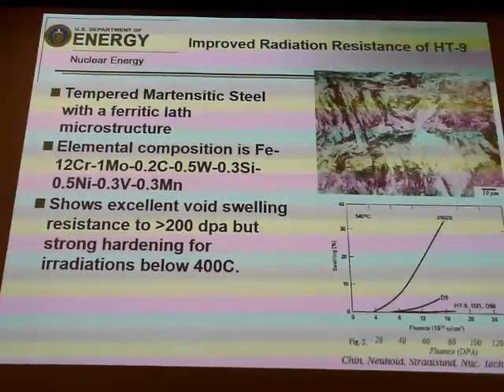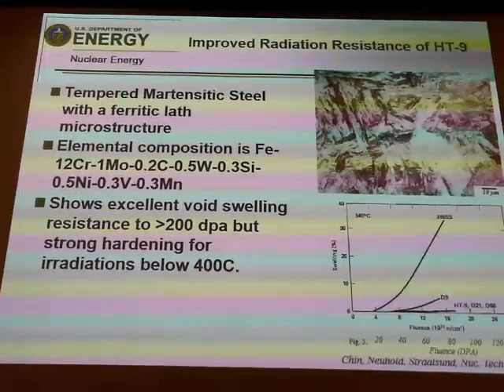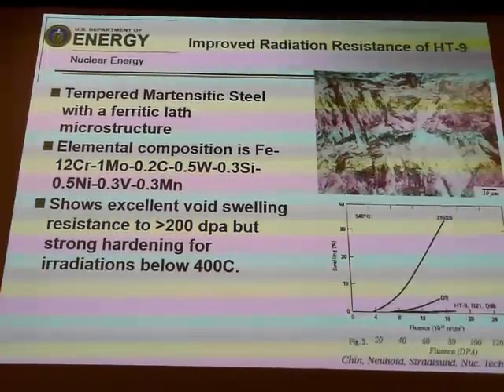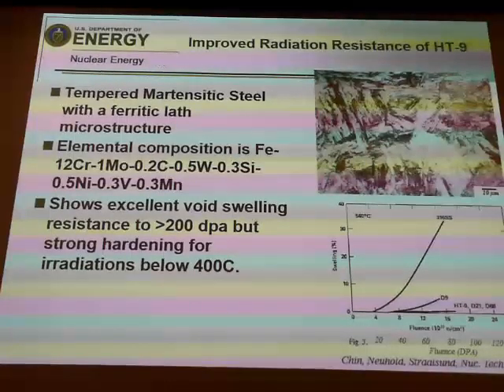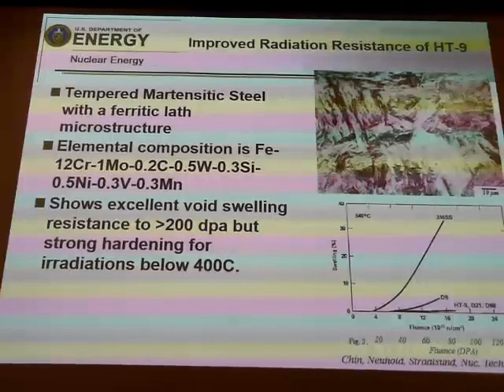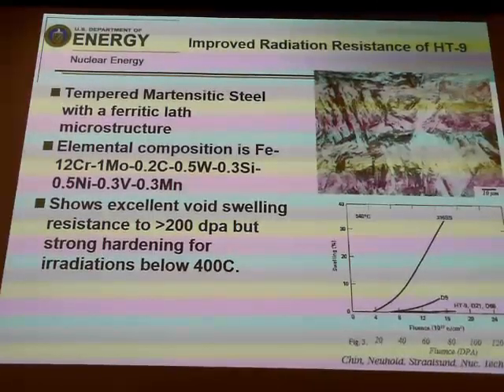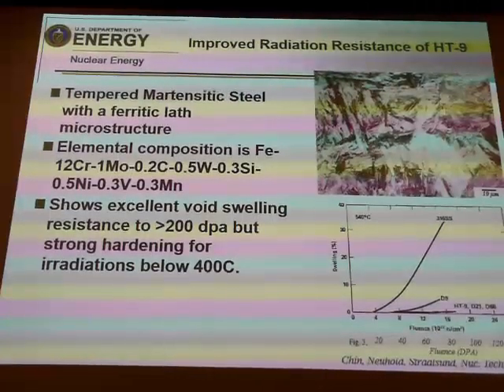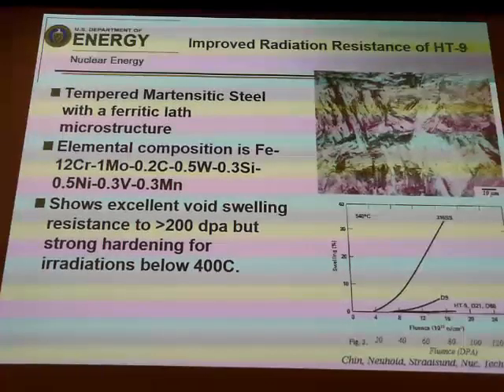And what is HT9? It's a tempered martensitic steel that has a ferritic lath microstructure. This is an optical micrograph of a typical tempered HT9 microstructure, and it's got a fine distribution of laths that are tempered to ferrite, and there you can perhaps see there are carbides at the boundaries, and there are also carbides at the lath boundaries as well. That large number of interfaces in the material serves as sinks for defects, and it's also all ferritic, so it's a BCC structure, which also helps from the standpoint of a reduced void swelling in the material as well.